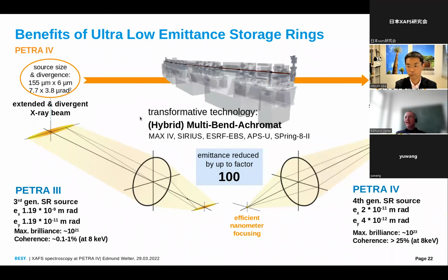And the storage ring at the ESRF was modified. The electron optics was modified to the ESRF EBS ring. It's all about achieving a smaller and rounder beam by reducing the emittance, mainly the horizontal emittance of the electron beam. That increases the brilliance of the beam, and allows to achieve a smaller focus and a much higher degree of coherence than we have at the moment at the third generation source PETRA III.